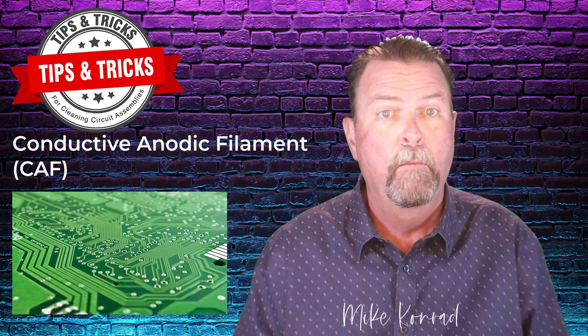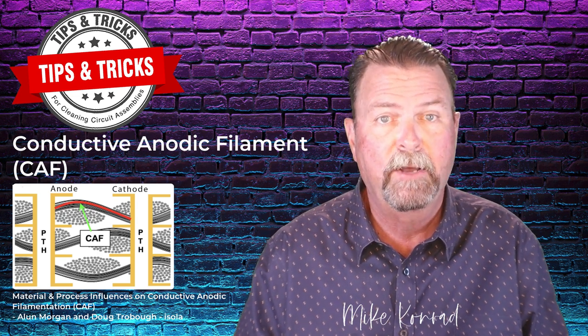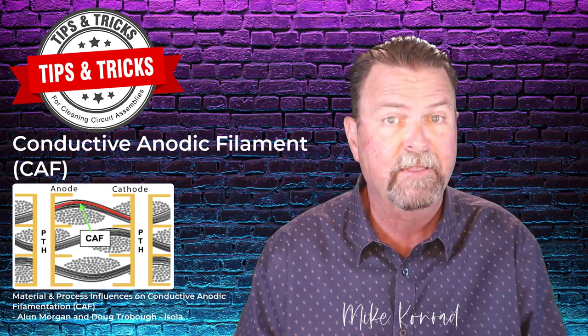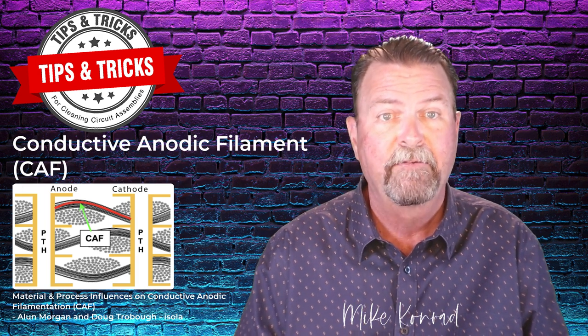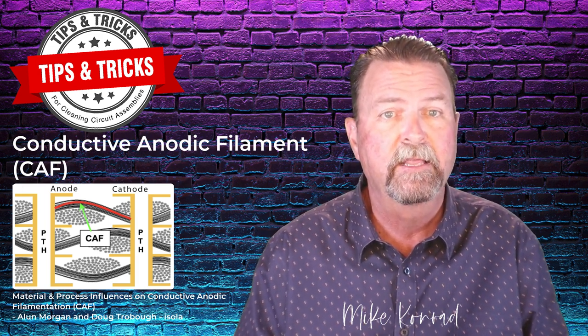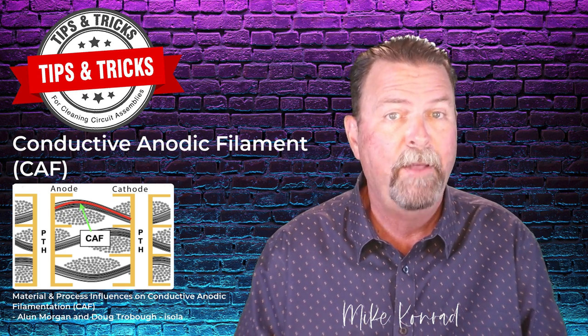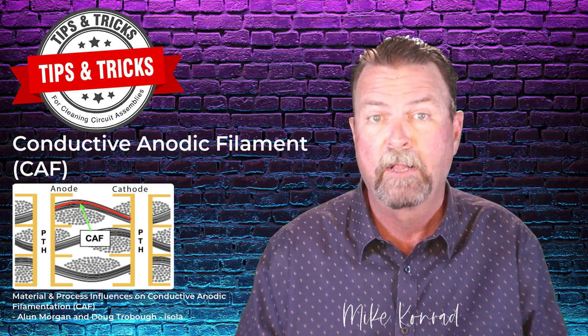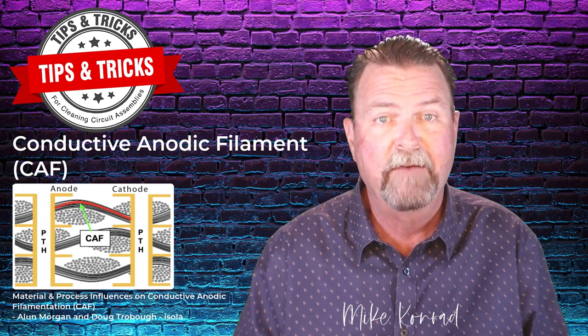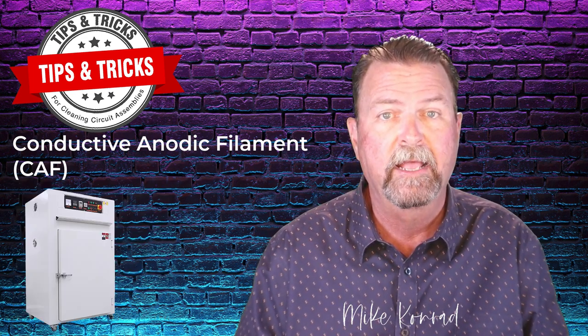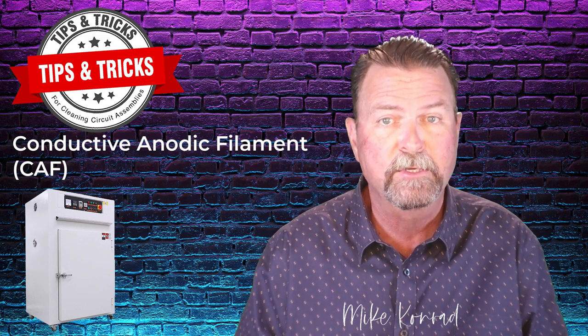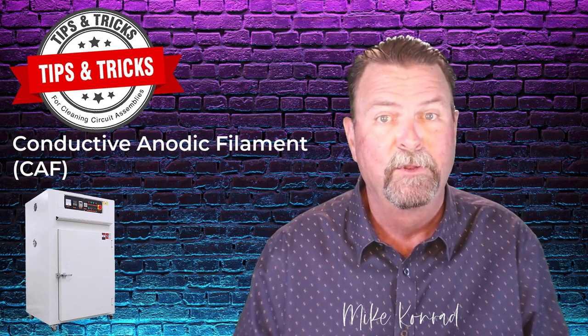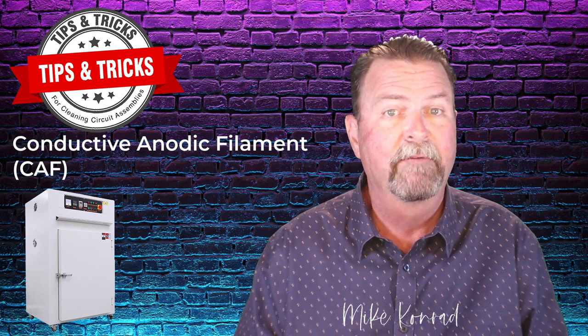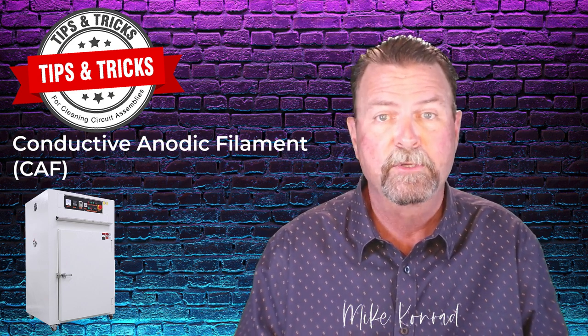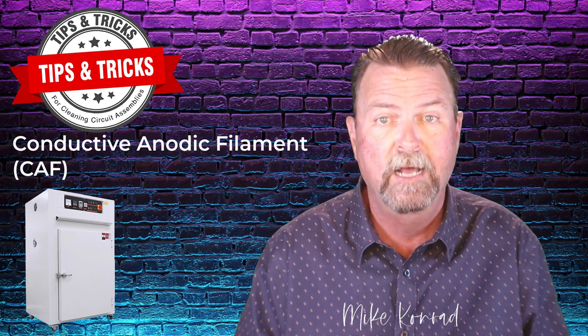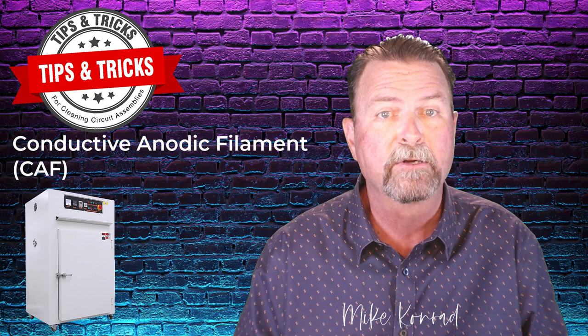While surface-level ECM can be prevented by performing a thorough cleaning process, CAF cannot be prevented by cleaning. CAF can be prevented by preventing the pathways from forming. If there are no pathways, the conductive plating solution will have nowhere to go. The potential for CAF can be mitigated or reduced by performing a thorough bakeout process to remove any moisture between the layers of the board. Remember, no moisture, no ECM. However, even if a bakeout process is performed, moisture can penetrate through the layers of the board over time, especially if the board is located in a harsh environment.